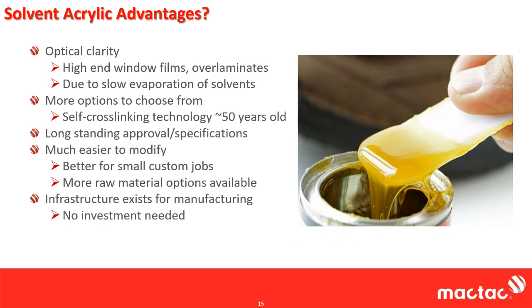That gets you probably 80% of the way there. But if you're talking true water white, which is a way of saying perfectly clear, you have no idea it's there, you can use it to laminate two pieces of glass together or have it as a glass over laminate and see no distortion whatsoever. That is really a function of your solvent-based adhesive and the solvents that really slow the evaporation. When you have those types of solvents that take a while to evaporate, everything has a chance to really get nice and settle down, kind of get smoothed out, and you get a really nice coating.